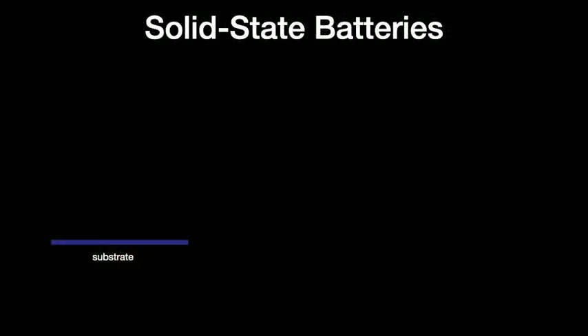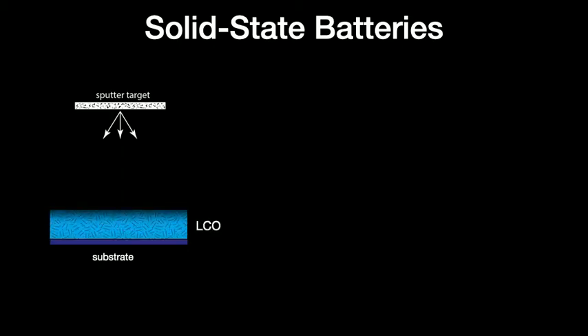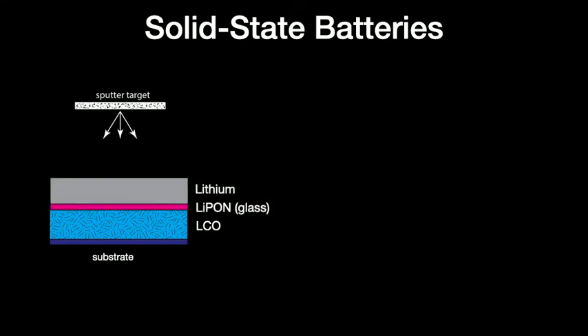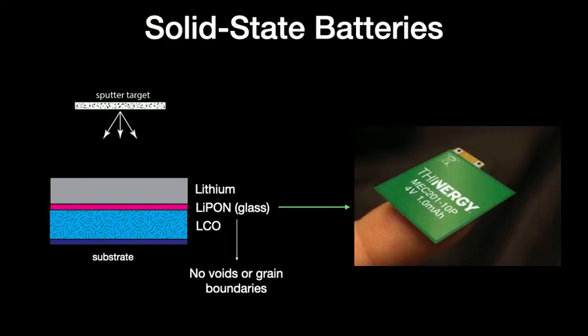Now we can look at another type of solid-state battery, which is actually called a microbattery, and it is done through sputter deposition. You have a substrate, you have a sputter target, you sputter down the cathode, then sputter down the solid electrolyte and evaporate lithium on top of that. The beauty of the glass is that there are no voids or grain boundaries. That allows you to build cells that look something like this. This is a commercial cell, which had a commercial spec of 10,000 cycles at 100% depth of discharge. This is desirable, obviously, but these are also expensive batteries because sputter deposition is slow and capital intensive. So that's not what you want to do. But there is something here, the use of glass electrolytes, that's interesting.